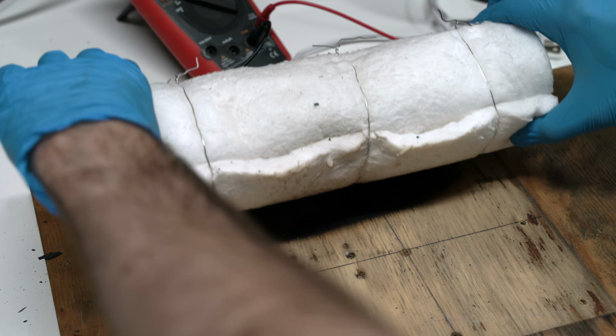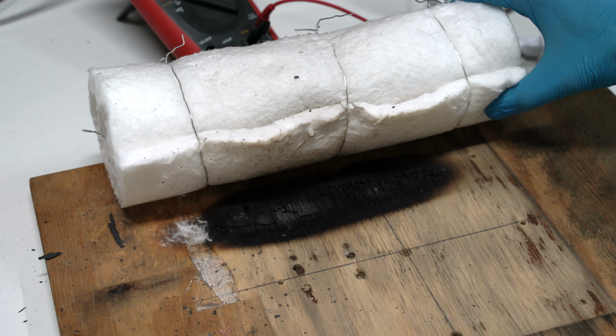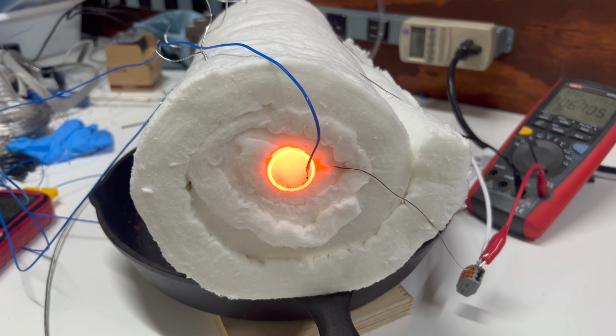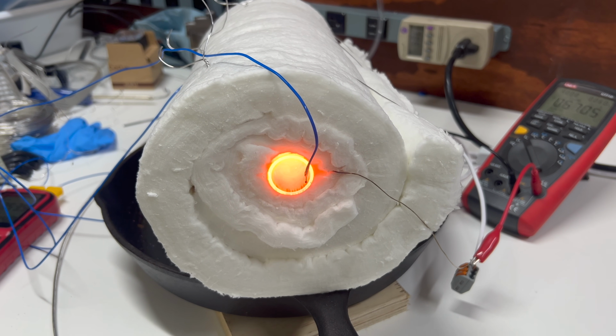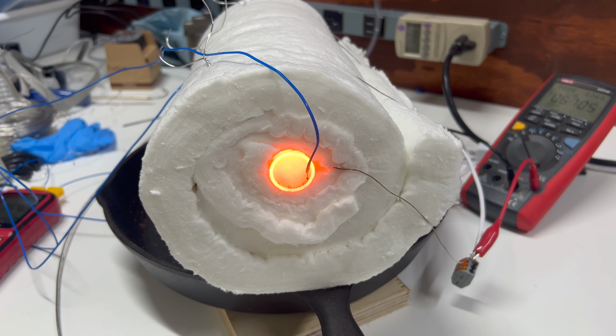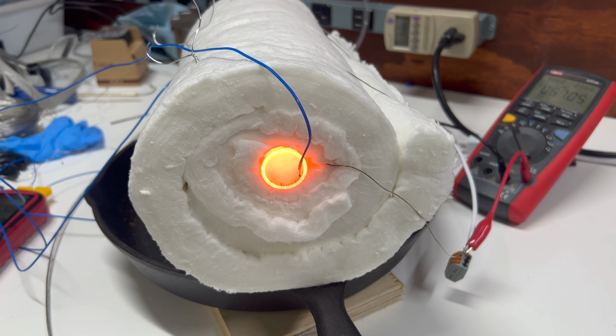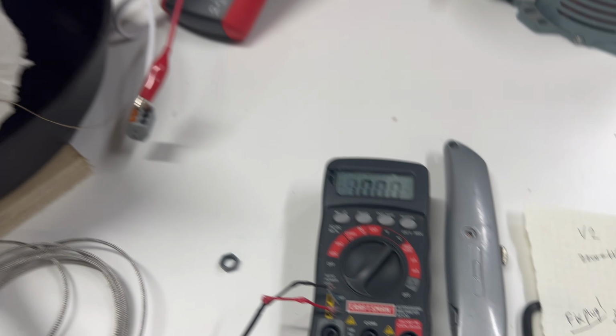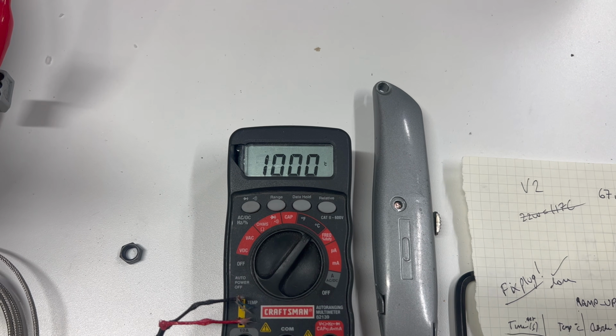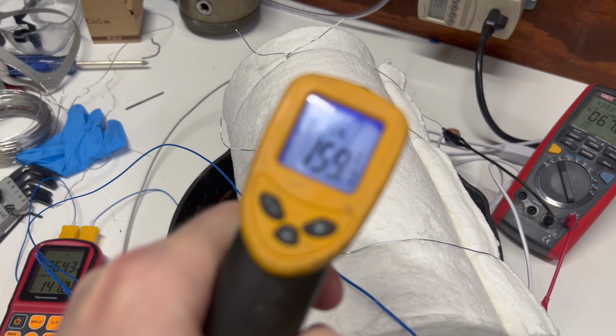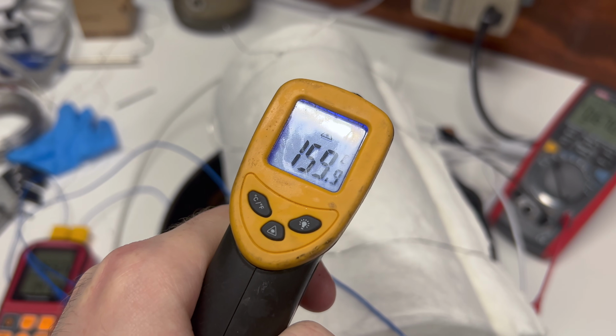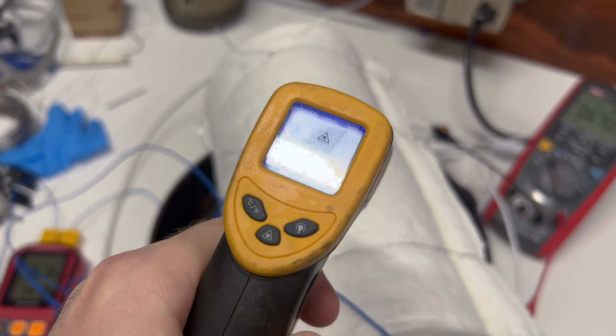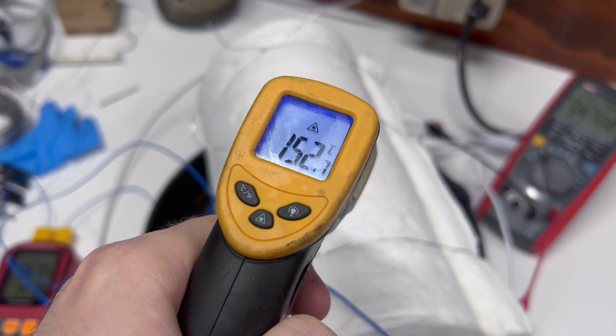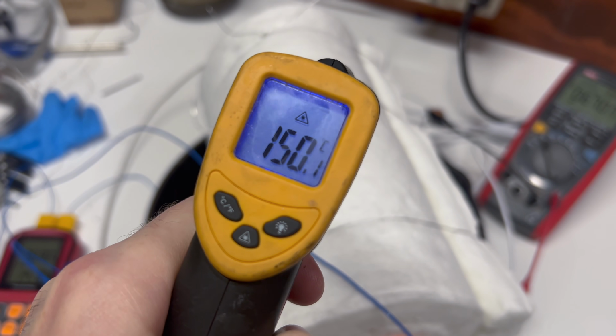Alright, well, the tube is cooled off. Let's check the damage. Ouch. I'm probably going to have to use more insulation than this. I added another inch of insulation, and I'm now resting it on a cast iron pan instead of a block of bare wood like last time. I once again brought the tube up to 1000 degrees Celsius, and it looks like the exterior of the insulation is only about 150 degrees. That's roughly 100 degrees Celsius less than before, so I think that's pretty good.